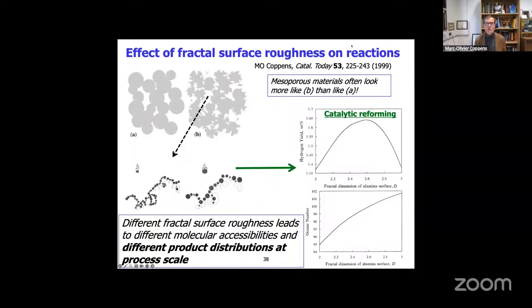Well, it matters really all the way to the macroscopic scale, even industrial scale of reactions. So going back to that platinum rhenium on alumina catalyst used in catalytic reforming, I predicted years ago that the hydrogen yield would depend on the degree of roughness of the surface. So you would have a maximum as a function of the fractal dimension.